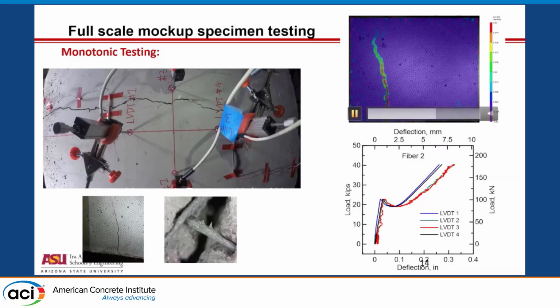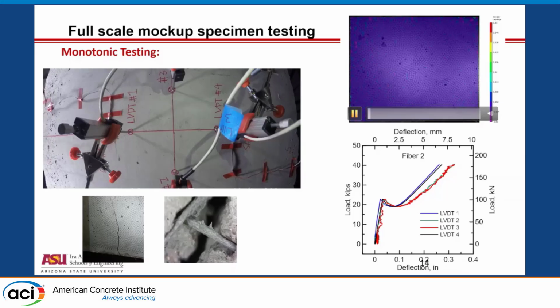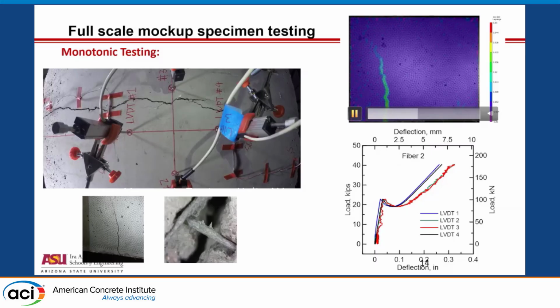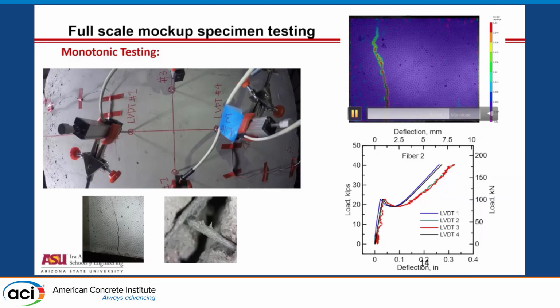So we can see exactly where the crack is forming and how it is propagating through, opening up, and that would basically be allowed as the mode of failure, single crack. Now, we can plot the load, and we see that even if you put 4 LVDTs, the responses are extremely close to each other, which means that we have a very nice uniform deformation.